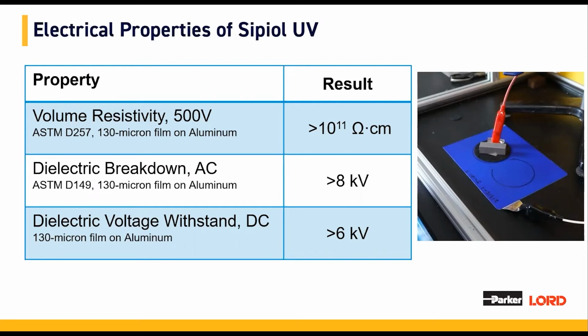Volume resistivity is greater than 10 to the 11 ohms centimeter when measured with 500 volts of applied direct current. This demonstrates that Sipiol UV is highly insulative. Dielectric breakdown when measured with alternating current via ASTM D149 measured 8 kilovolts of breakdown voltage on a 130 micron film. This equates to a dielectric breakdown of 60 kilovolts per millimeter.